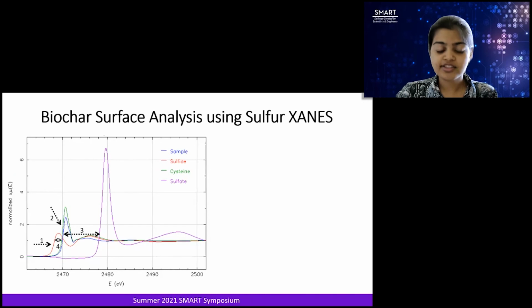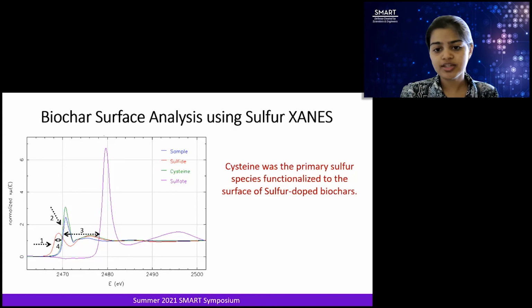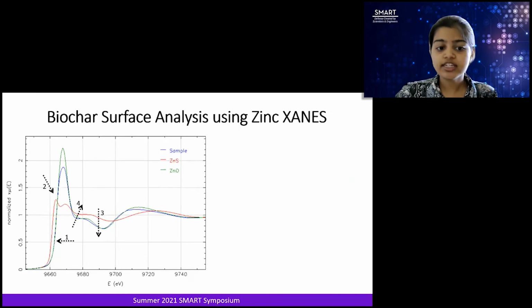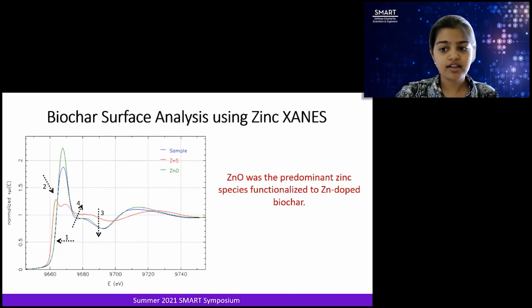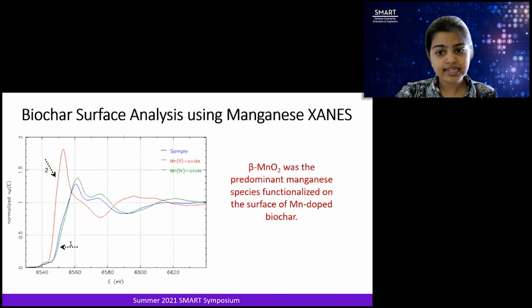I then analyzed the surface of the biochars using X-ray absorption near edge structures. And here you can see the sulfur XANES for enhanced biochar, from which we can see that cysteine was the primary sulfur species functionalized to the surface of sulfur-doped biochars. Similarly, for zinc XANES, we can see that zinc oxide was the predominant zinc species functionalized. And lastly, for manganese XANES, we can see that beta manganese oxide or pyrolusite was the predominant manganese species functionalized. This tells us that the biochar doping was successful.